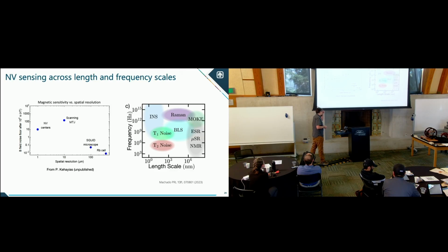So I want to give you the scale too of where the NV sensing sits relative to other quantum sensors. And pardon me if I've offended anyone on sensitivities, but this is approximately it qualitatively, particularly for spatial resolution versus the magnetic noise floor. So how sensitive you are. Better sensitivity means lower magnetic field noise, and then spatial resolution goes down in this. And so, vapor cells have an extremely good sensitivity, but their spatial resolution isn't so high, right? So you're very susceptible to magnetic fields, but you can't accurately pick them out. Squid magnetometry, and this is mostly for at room temperature. And for example, scanning magnetic tunnel junctions, you're starting to go lower in spatial resolution, but also higher in your magnetic noise floor. And so NV centers sit about here.